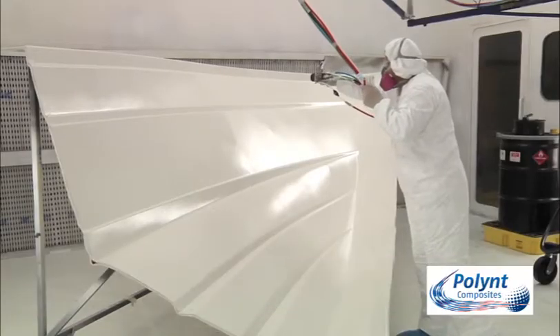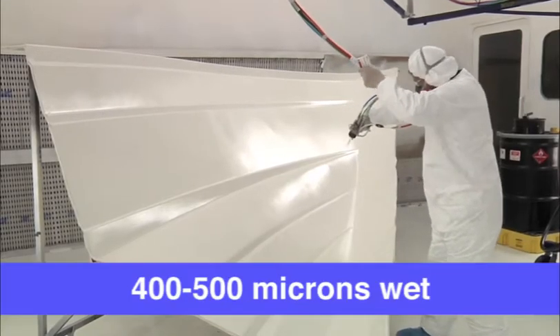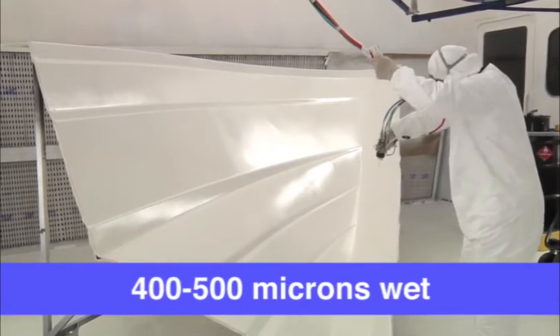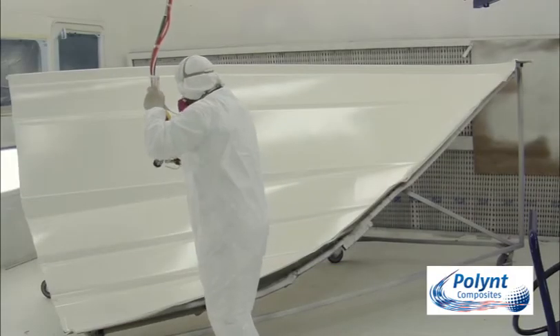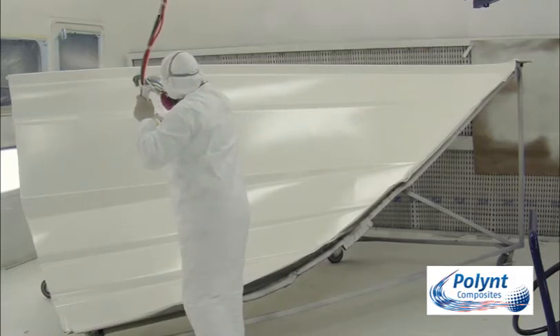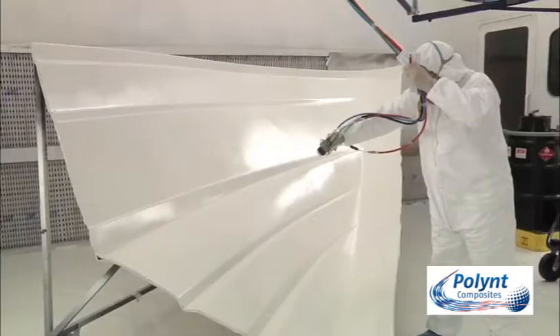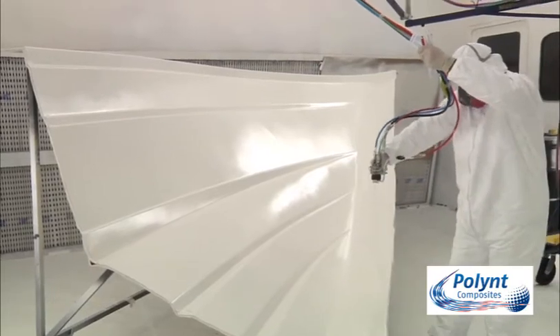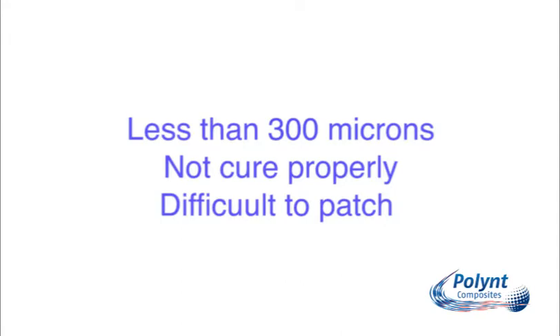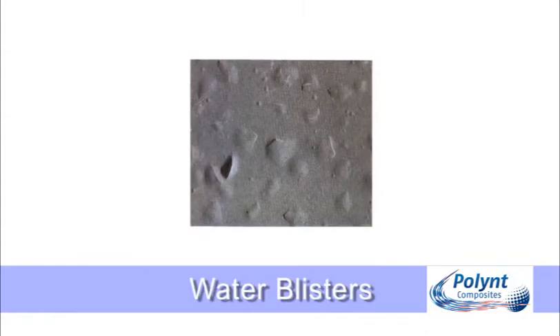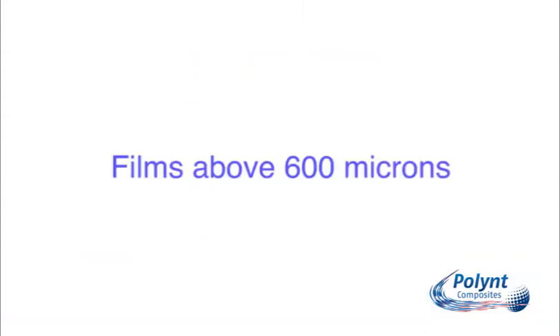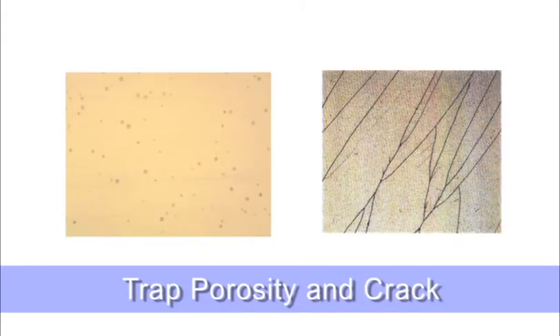Spray a total of 3 passes to achieve a total thickness of 400 to 500 microns, wet measured with a micron gauge. When practical, spray in sections from one end, working continuously to the other. Avoid overspray onto other parts of the mould. Films less than 300 microns may not cure properly and will be difficult to patch, show fibre print through, and are susceptible to water blisters. Films above 600 microns may pre-release, trap porosity and crack, and are subject to weathering discoloration.